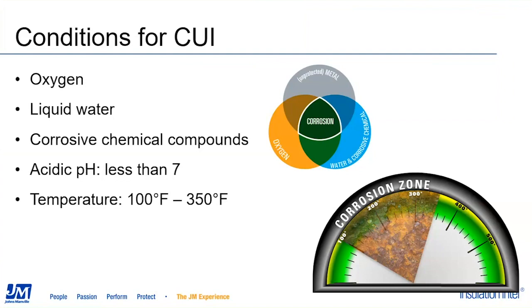You do need a corrosive environment, and that can be either corrosives entering the insulation system from the outside environment, or potentially corrosive compounds or materials being leached out of the insulation system itself. And you need that to be acidic, or to have a pH of something less than 7. And then the system needs to be operating in what is referred to as the corrosion zone, which is typically considered to be the temperature band between 100 and 350 degrees Fahrenheit.